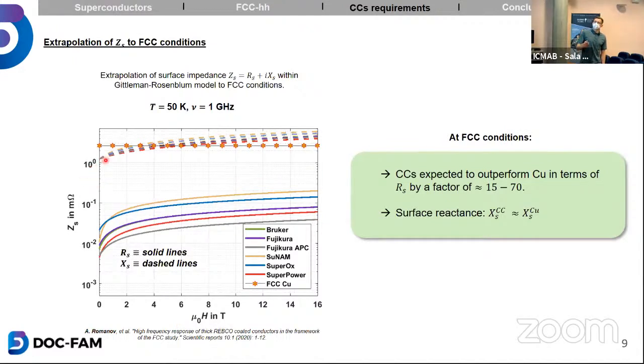And if you now compare the surface reactance of the coated conductors, these are the dashed lines, I didn't mention it, with the surface reactance of the copper, these are the stars, you can see that they are always in the same order of magnitude, right? At small fields, the coated conductors have a lower surface reactance. At higher fields, they are slightly higher, maybe by a factor of 2 to 3, but they're in the same order of magnitude. However, if you look at the surface resistance, we outperform the copper with the coated conductors by at least 1 order of magnitude, close to 2 orders of magnitude.